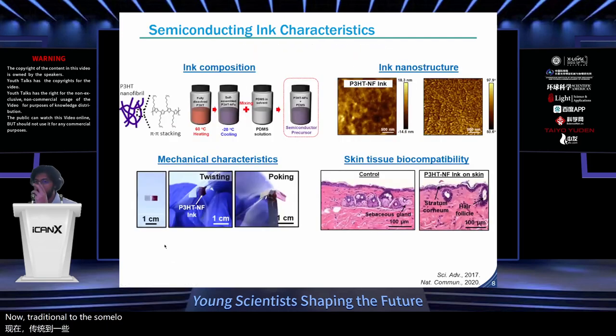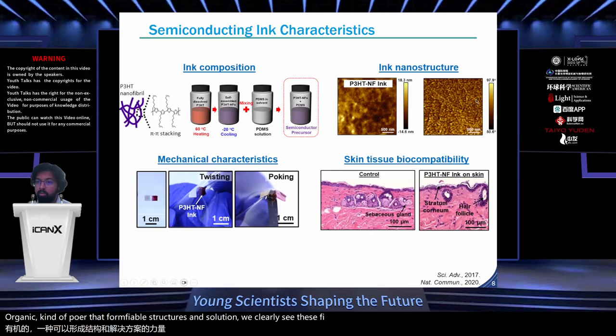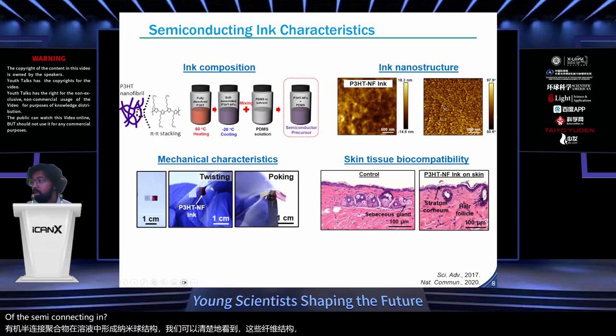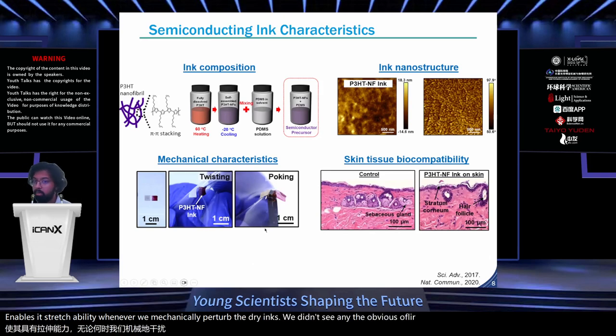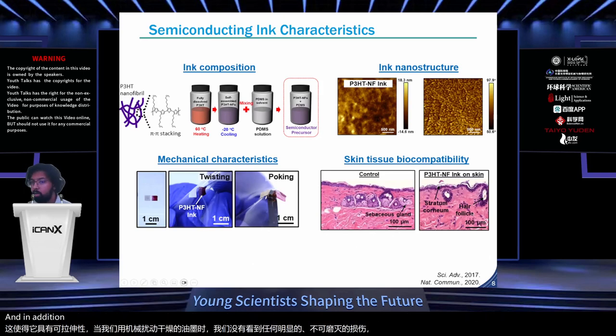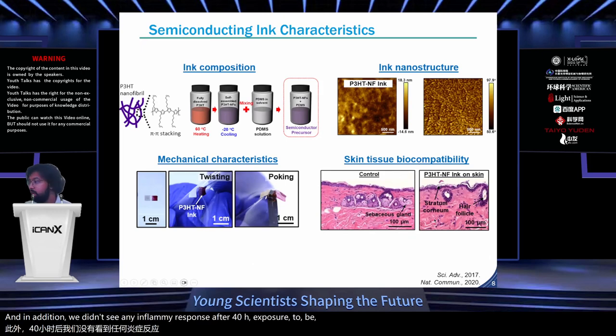Now, transitioning to the semiconducting ink, we use an organic semiconducting polymer that forms nanofibril structures in the ink. You can clearly see these fiber structures in the semiconducting ink image, which enables its stretchability. Whenever we mechanically perturbed the dried inks, we didn't see any obvious observable damage. And in addition, we didn't see any inflammatory response after 40 hours of exposure on the skin of mice.